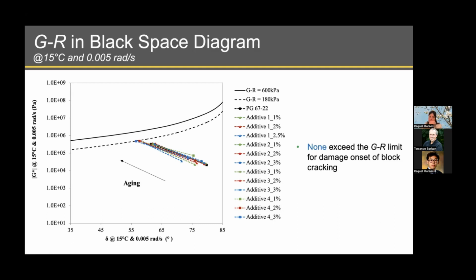We have to say that these thresholds were defined in field experiments for unmodified asphalt binders. So the applicability of these limits for binders that are modified with any type of additives needs to be validated. But what we can see is that for all of the binders, before and after long-term aging, for the base binder and for the binder modified with the graphene additives at all the evaluated dosages, we did not see any of the binders in the cracking damage. So none of the binders show potential for cracking.